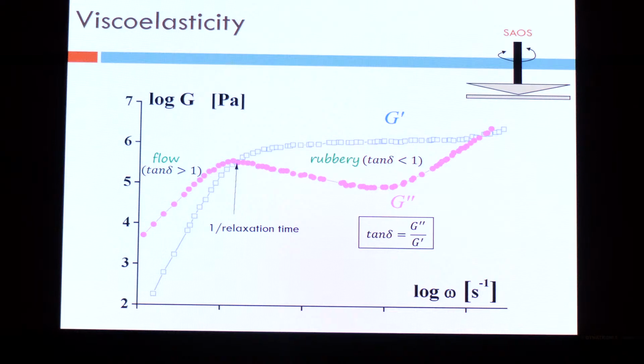And so on the left side, when you are flowing, the tan delta is greater than 1 because G double prime is higher than G prime, so the tan delta is higher than 1. On the right side, in the rubbery plateau, the tan delta is less than 1. Okay? So in later slides, I'm going to talk about tan delta, and you just have to remember that when tan delta is decreasing, it's becoming less than 1, I will get more elastic response.